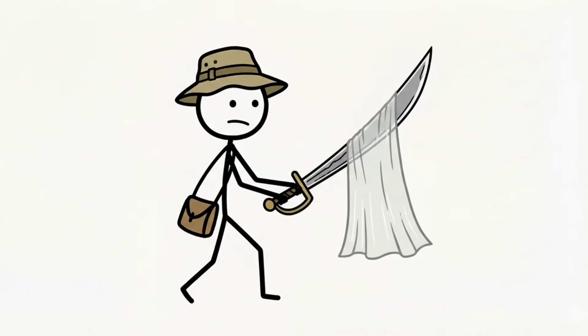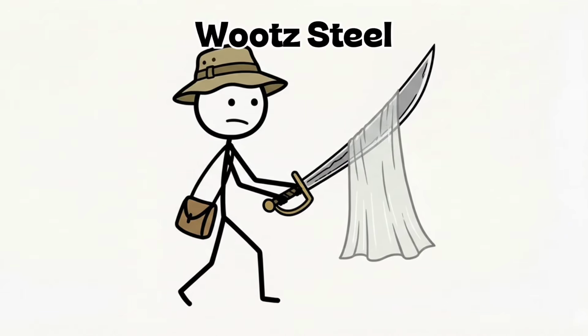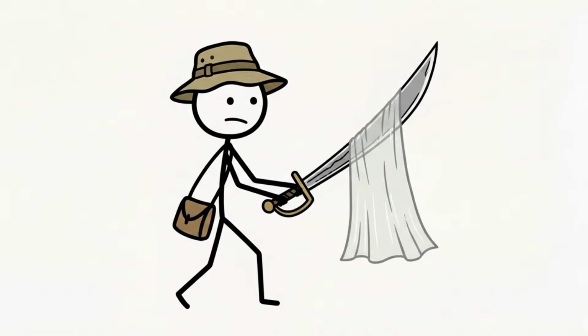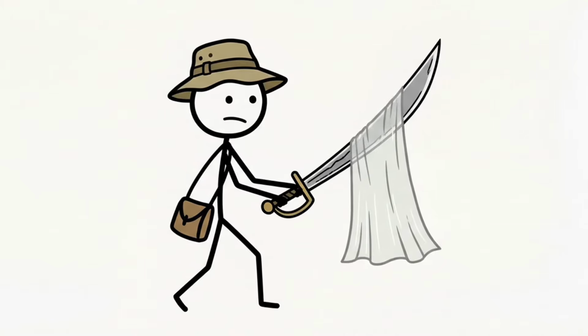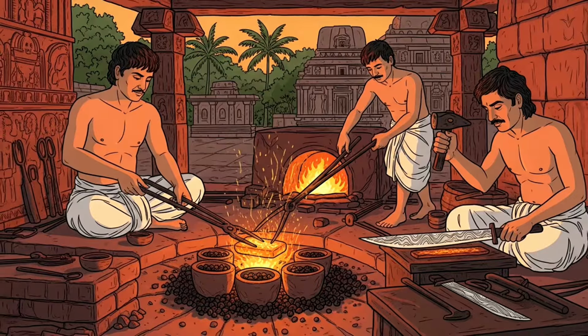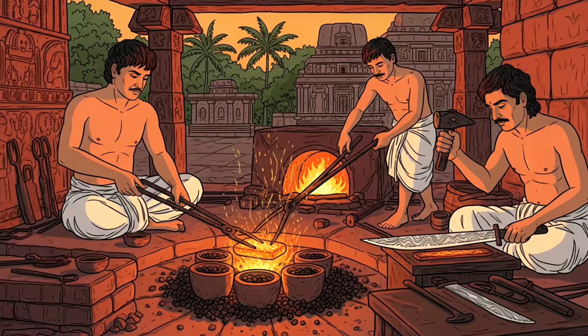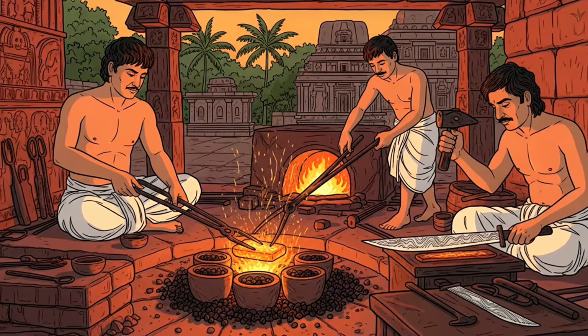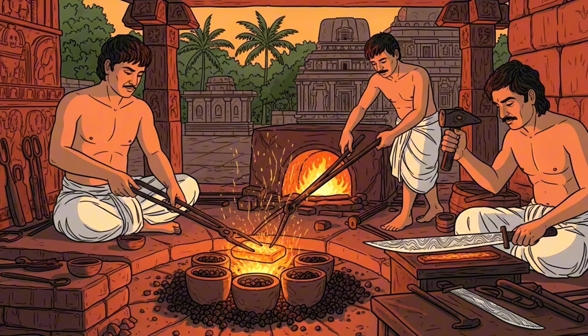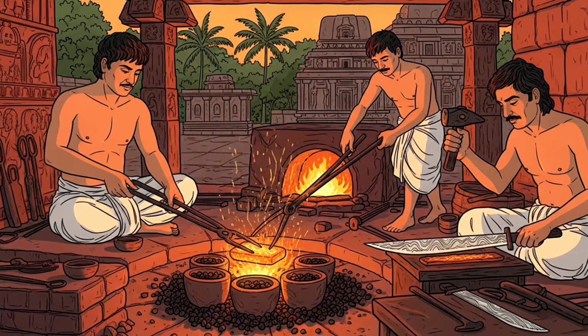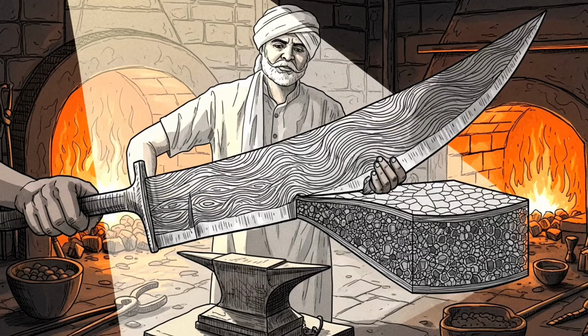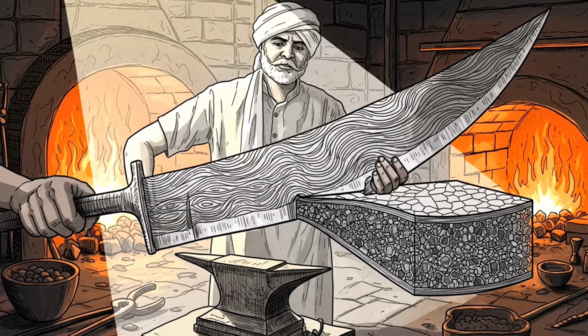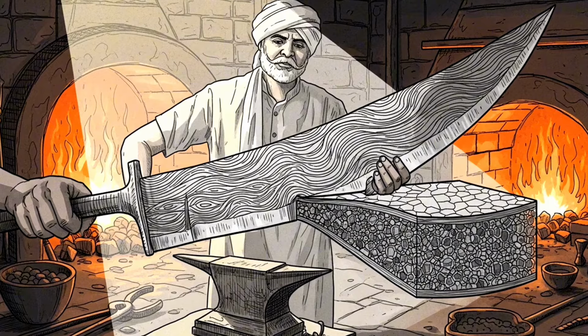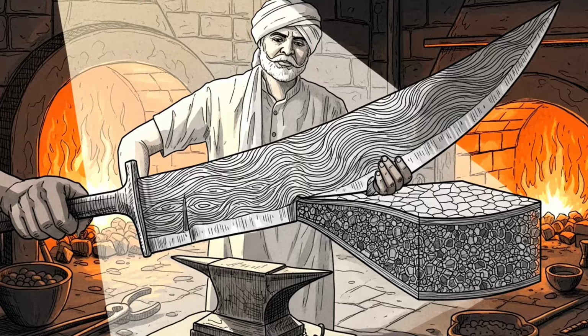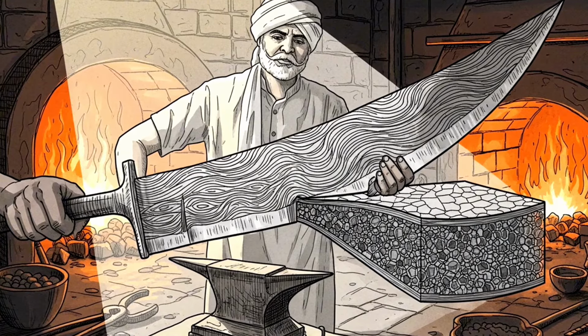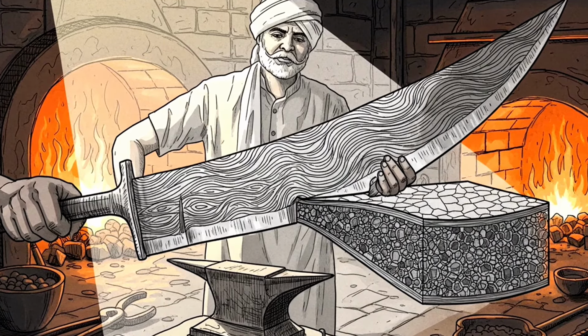Number 6. Wootz Steel. A Wootz blade could slice a silk veil in midair and shatter a standard iron sword on impact without taking a notch. This steel was developed by the Chera, Chola, and Pandya dynasties as early as the 6th century BC in South India, making it among the oldest high-carbon steels in the world. The distinctive wavy lines visible on a polished Wootz blade, often called the water pattern, are the surface expression of an internal crystalline microstructure running through the steel's core.